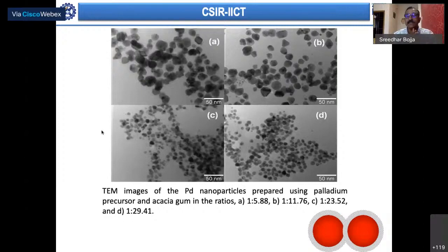But there is another thing which was interesting: how does concentration of gum solution influence the size of these particles? How does the concentration of gum acacia solution influence the size of these particles? We observed that at lower concentration, the size of the particle is big. As we increase the concentration of gum acacia, they stabilize to 8 to 10 nanometers, and that is the maximum, minimum size that we could get.